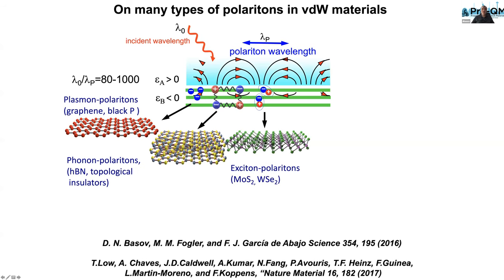If you are interested in lattice dynamics, then phonon polaritons, also supported by van der Waals solids, are your friends perhaps. Phonon polaritons are very interesting in this class of materials and could be a topic of a separate talk. In particular, they enable so-called hyperbolic behavior when waveguide modes travel through the bulk of a crystal in the infrared active phonon modes, and in bulk three-dimensional crystals, this type of waveguiding is prohibited. But these layered materials, they support it, and these modes are quite exciting.